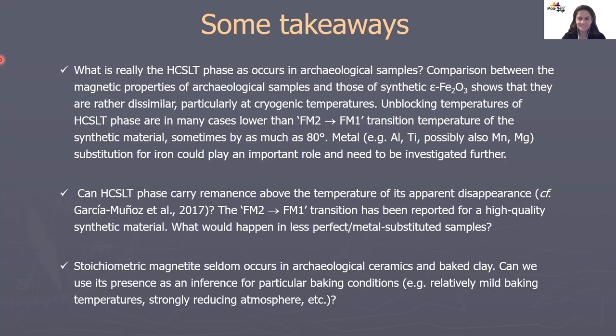So I guess my question is, you described the epsilon phase as having an apparent Curie temperature, which is maybe related to a change in the phase. How might you expect that to manifest in a remanence experiment, like a paleointensity experiment, for example? Well, I would rather hope it would not have a great effect, because the high temperature phase of epsilon is much weaker than the low temperature one. In real samples, I would believe it would not be distinguishable from maghemite or hematite, because the coercivity range would be approximately the same. But it would be curious to investigate that in synthetics.